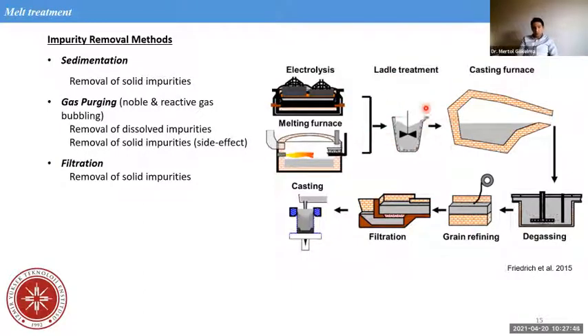It goes first to the ladle treatment, such as alloying, and then the casting furnace. In the casting furnace, there will be some homogenization, skimming of the oxide skin, dross, and sedimentation. Afterwards, the degassing process to remove hydrogen and alkalis, grain refining, filtration, and casting. So that's why melt treatment can be used both for primary and secondary melts in case they need that.